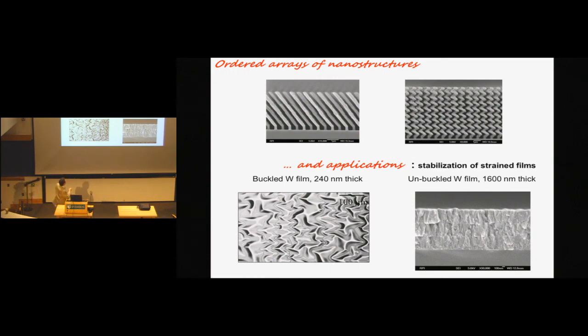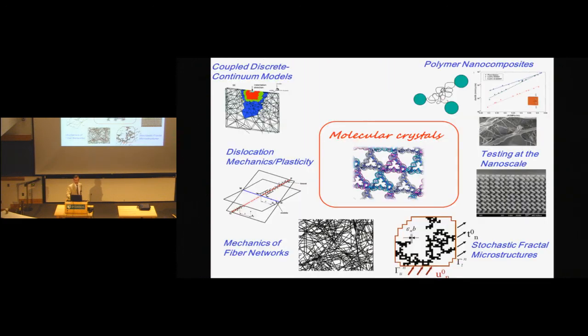So we came up with the idea of actually using nanostructures for that purpose. So what we did is consider a silicon substrate, grow a layer of nanostructures, which you can't really see over here. You grow a layer of this type of structures on the silicon. Then you just rotate the source, and you keep growing. By the way, the nanostructures are from tungsten as well. You rotate the source, and you keep growing normal film. Okay? You grow for about 200 nanometers. Everything is stable. Then you rotate the source, and you grow nanostructures, another layer over here, and then you grow normal film, and another layer of nanostructures, and another layer of normal film. And after more than a micron and a half, the film is still stable. So basically, the presence of that layer of nanostructures in between is actually releasing the stress somehow. It's a compliant layer which is releasing the stress. So you can grow stable films without much technological new requirements from the technology side.